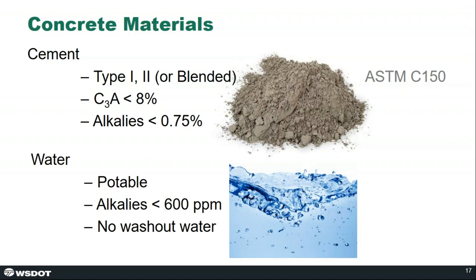And when it comes to water, we basically require potable water. There's an alkali limit on the water for similar reasons. And for bridge decks in particular, we restrict them from using washout water in their ready mix trucks. So after a truck returns from the job site empty, they'll wash it out, and we don't allow them to keep the water in the tank for the next batch of concrete.